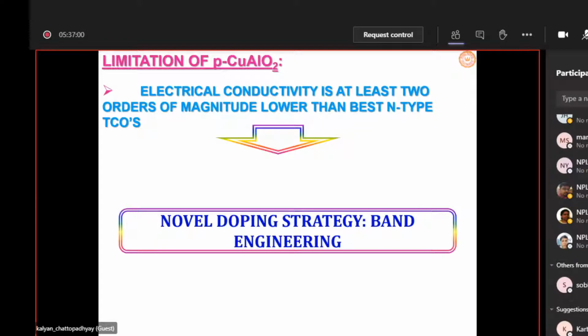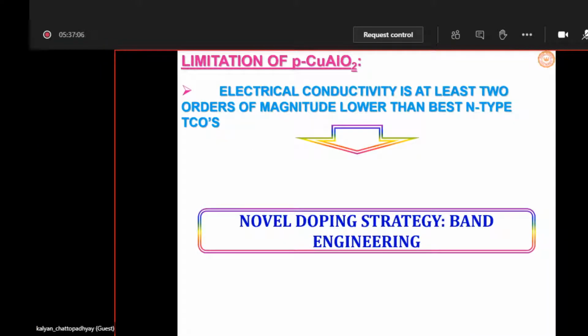So what to do? This is actually the conductivity bottleneck of this P-type TCO. We thought over this problem, and we thought that it is not sufficient to achieve only valence band dispersion. Even if the valence band is dispersed, it is still very difficult to move the hole.